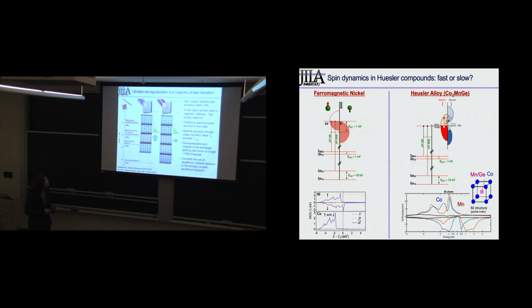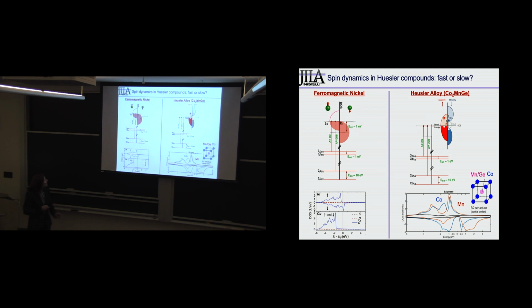And then we thought, well, okay, this idea of using the laser to heat electrons well above the Fermi level, and then having some relaxations to make magnons, that would be very different in one of these Heusler half metals, because some of these scattering channels would be blocked. So what we all thought going into this is that all these blocked channels would mean that we wouldn't be able to manipulate the polarization in the Heusler metal very fast. So we all expected this to be a much slower loss of magnetic order.